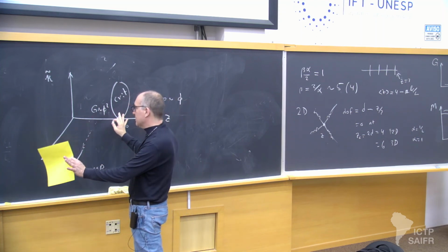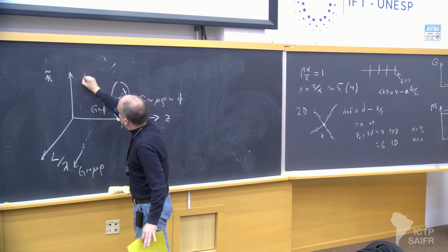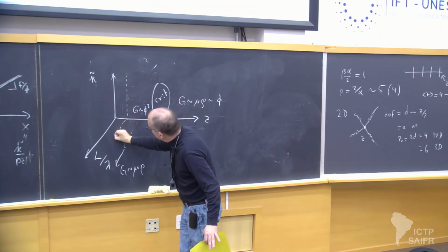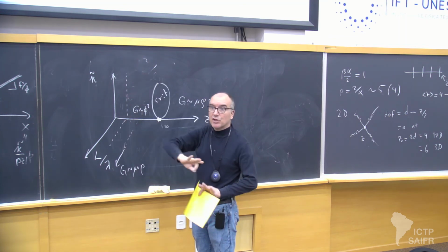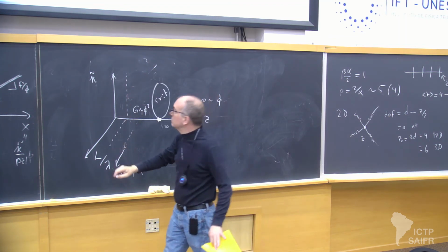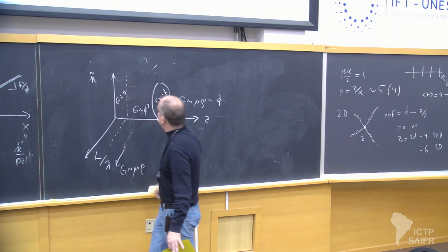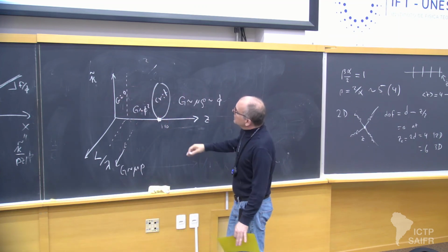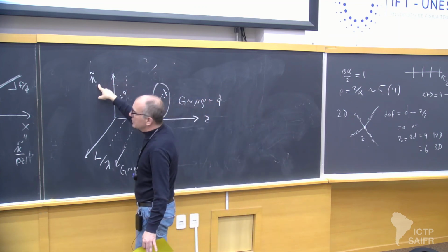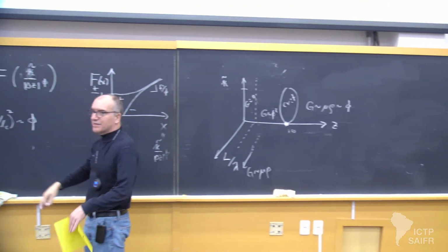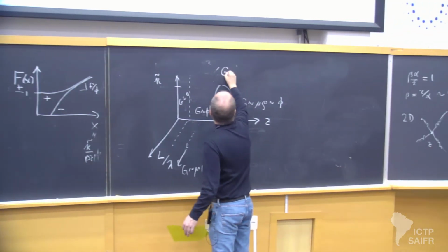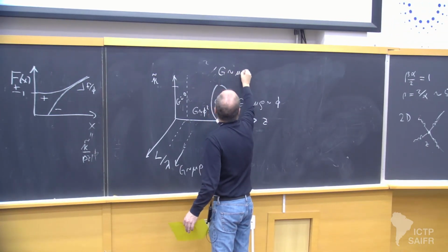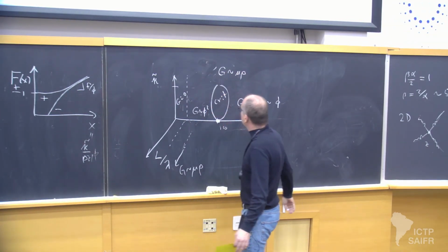It's all linear elasticity still. There's actually a phase boundary over here, which is that lower connectivity point. Below that, there's no modulus at all, ever. G equals 0. And of course, if kappa gets really large, if this dimensionless measure of kappa gets large, I suppress all bending, and I just go back to a G proportional to mu rho. I still have my stretching.